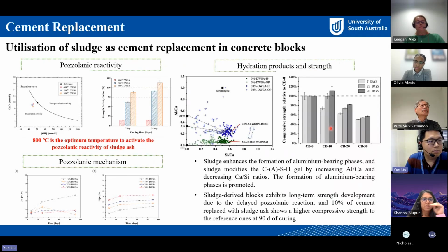The pozzolanic reactivity of sludge was measured by the Frattini test and the strength index test. Based on the results, we can find that sludge after calcination at 700 and 800 degrees shows satisfying pozzolanic reactivity, but 800 degrees is the optimum temperature to activate the pozzolanic reactivity of sludge ash.